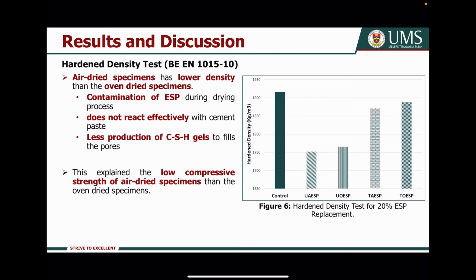Next, the air-dried specimen has lower density than the oven-dried specimen. This is due to the contamination of ESP during the drying process, making it not react effectively with the cement paste. Therefore, there is less production of CSH gel to fill the pores. This explains the low compressive strength of the air-dried specimen than the oven-dried specimen.